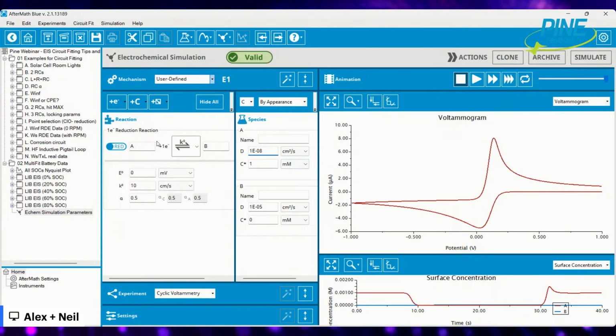Well, in this case, A is reducing to B with a 1 electron process, but the A species, for whatever reason, has a much smaller diffusion coefficient than the B species. And so what that leads to is a much lower and more broad Cottrell diffusion characteristic on the reduction side than the oxidation side. So what it looks like is an uneven amount of current on the peaks. I just wanted to throw that out there because I don't know if that's precisely what you mean, but that's just one. It could be mismatched diffusion characteristics, so to speak.